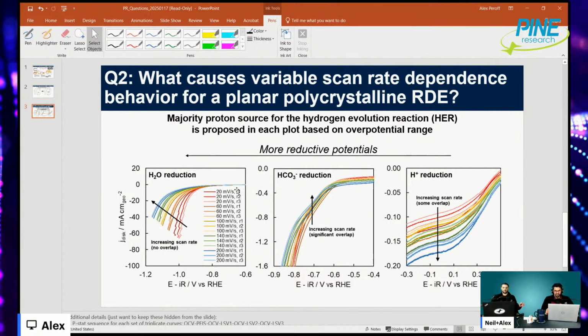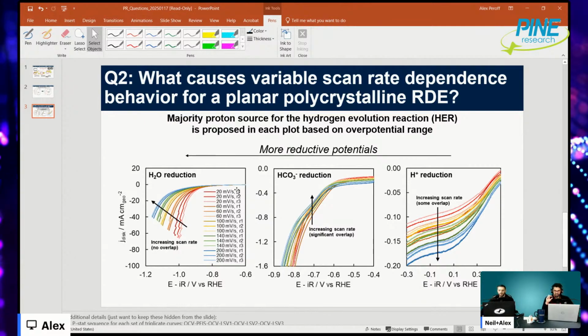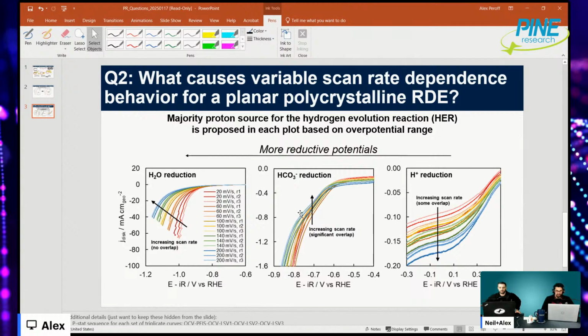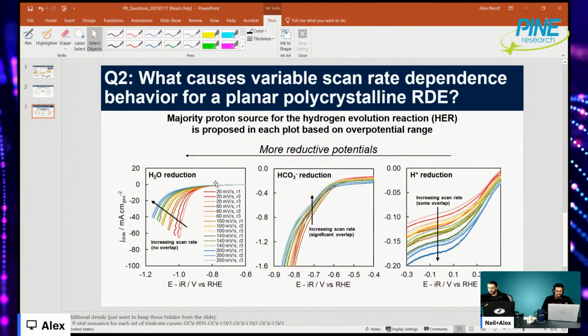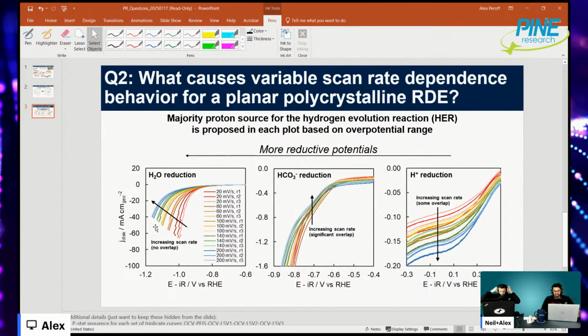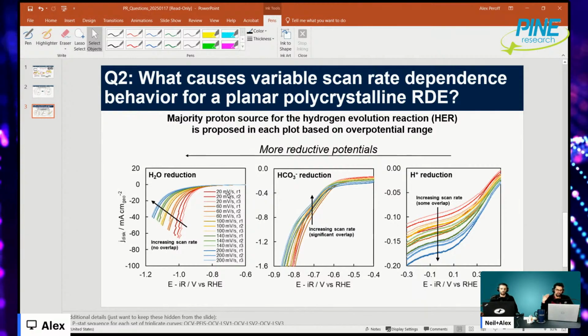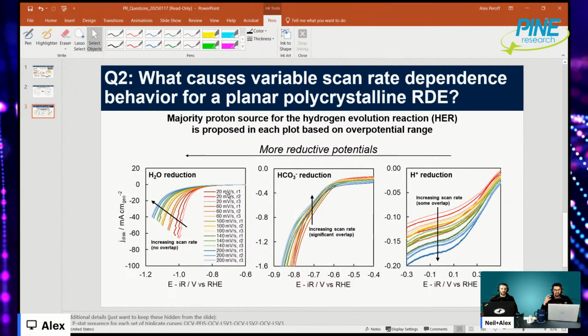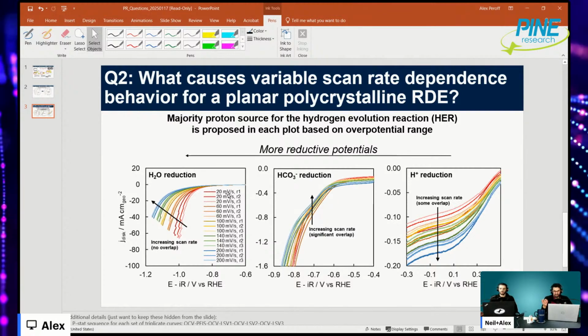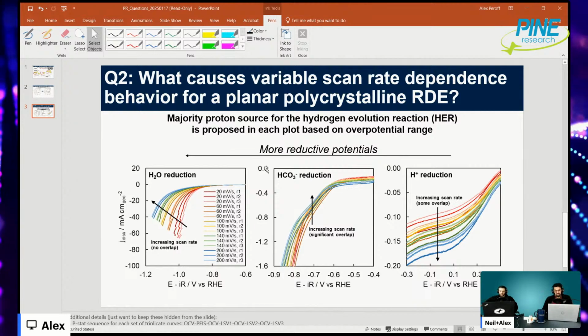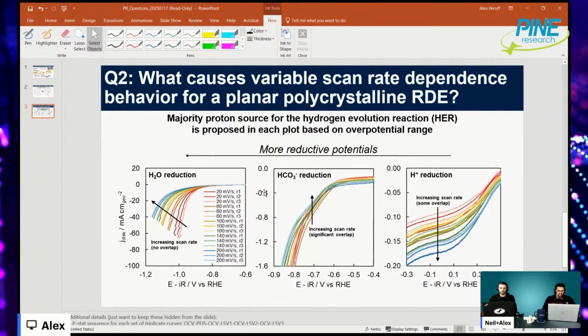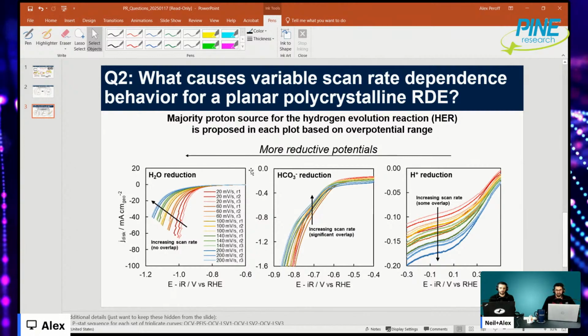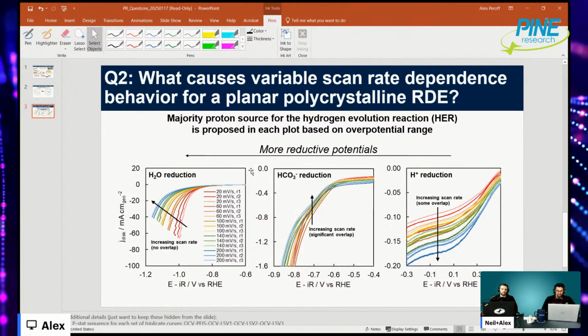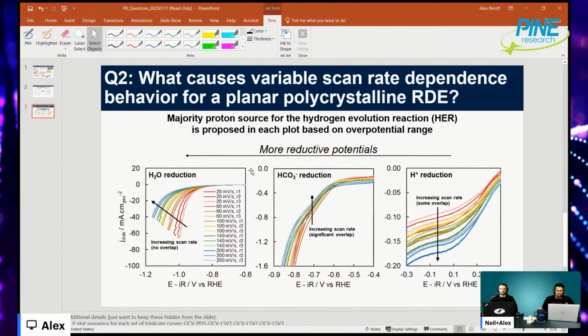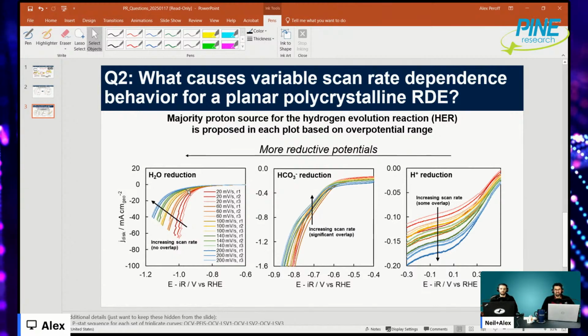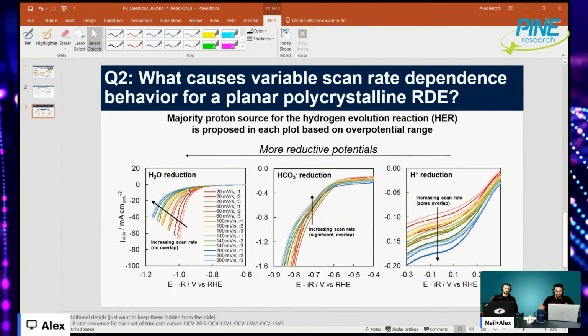You can just do a chronoamperometry experiment and literally take one data point at a time, and you should be able to get these same curves. And when you start to scan at fast scan rates, you deviate from it, and you would see that if you go to very, very fast scan rates, your LSV curves will start to look more like voltammograms, and have characteristic signals of voltammograms, which include capacitance or double layer charging,